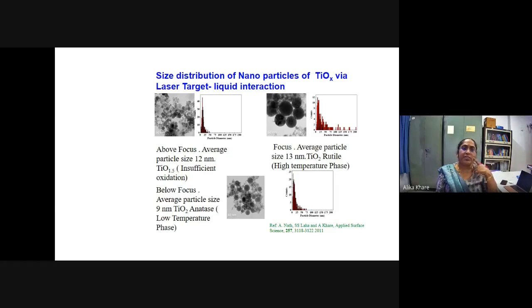So here I would like to share results from some of my students. This is titanium oxide, formation of titanium oxide particles. Under different conditions, we get different kinds of titanium oxide, its phases as well as its oxygen content. Under certain conditions, we get highly insufficiently oxidized titanium oxide nanoparticles - so this was TiO 1.5 here. Here is TiO2, but in the anatase phase. And under some other condition, we got TiO2. So here we just controlled the laser power, by changing the focusing spot onto the target, and we got these three different phases.